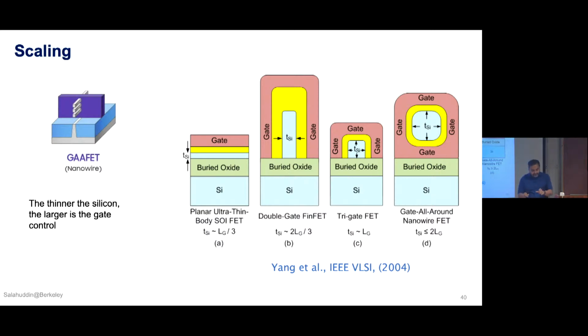It takes a little bit of work with Poisson's equation to see this, but there is an intuitive way of looking at it. If you have a silicon sheet and you have gate from two sides, the longest distance from the gate is the middle part of your sheet, right? So if you reduce the thickness of the sheet, the longest distance becomes shorter, so the gate gets more control. When people did these calculations a long time ago, solving Poisson's equation, they said that in principle you could reduce your gate length to thickness over 2, which means for our demonstration, 3 nanometer, you can get down to an LG of 1.5 nanometers.